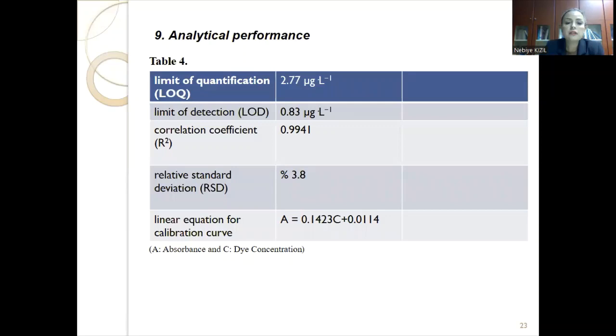Now, finally, analytical performance criteria were calculated, like limit of quantification, limit of detection, correlation coefficient, relative standard deviation, linear range for the calibration curve. We can see from the table, we achieved low limit of quantification and limit of detection.